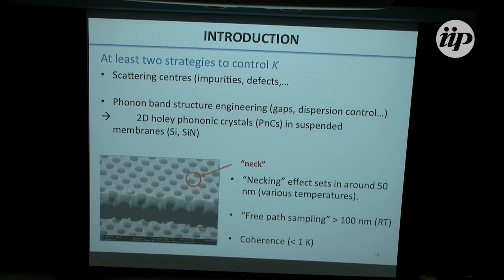So flat dispersion relations. And in particular, we decided to work with holey phononic crystals, this type of membranes with holes, suspended, and basically the community is working on silicon, silicon nitride, gallium arsenide, etc. You will see that one of the key parameters, geometrically speaking, is this neck. And the neck here is defined as the material between two holes in the pattern. Right? So we will see that our neck effects are set around 50 nanometers, depending on temperature.